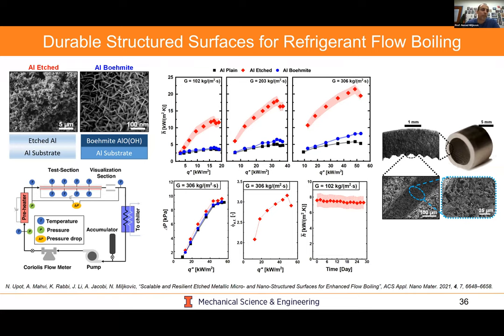And so in this case, typically what people will do is they'll use oxide-based formulations to form an oxide with a particular structure on a particular substrate. What ends up happening is you then form a distinct interface between the pure metal substrate and the oxide, which you're putting on top. These have different coefficients of thermal mismatch. They have different properties. They have different solubility in different fluids. One thing we've been looking at is how can we actually crystallographically etch metals to form a metal structure, which could actually be durable enough, but also large enough to be relevant for flow boiling.